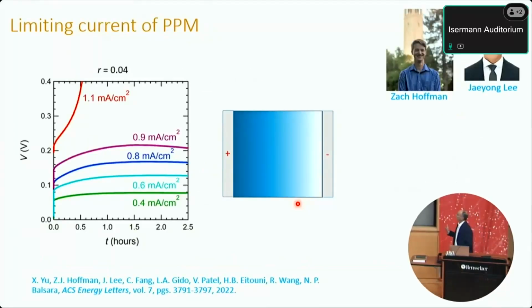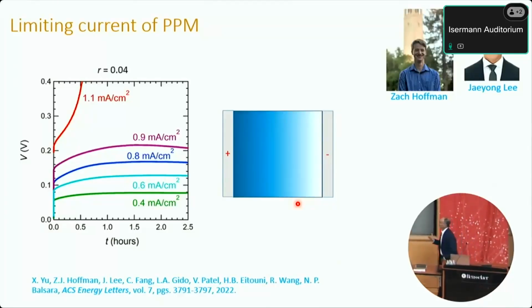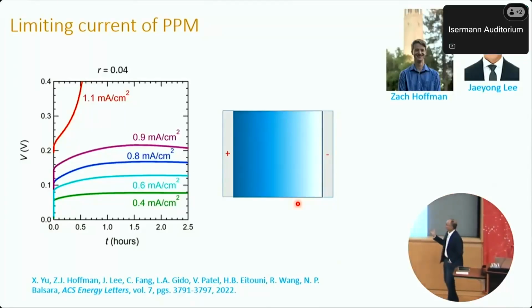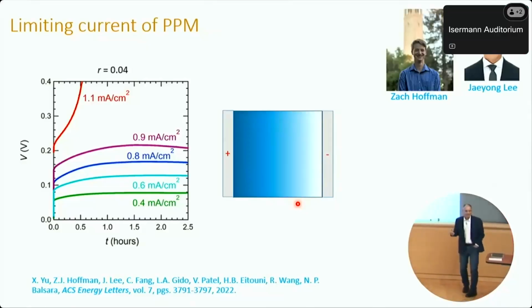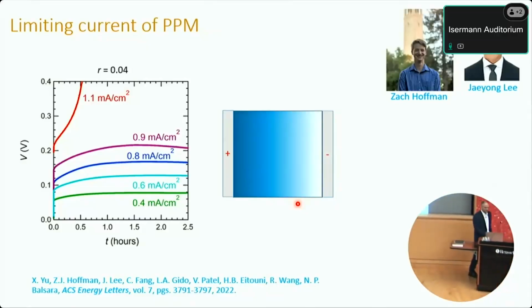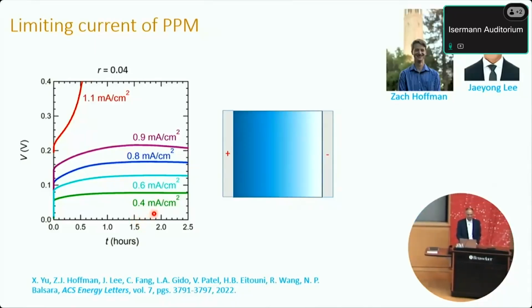So here are some experiments that Zach and Jae-young did. You take this electrolyte in the battery, you start charging a current. At fixed current, you get a certain voltage profile as a function of hours, and you ramp up the current, and up to 0.9 milliamps per centimeter square, you get a stable voltage. You might not even call that stable, but this is what we call stable. And then you go to 1.1 and something dramatic happens. Okay, the voltage diverges.